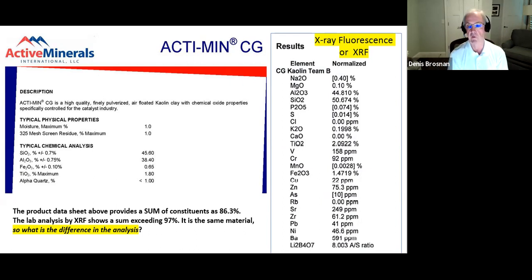Well, this full analysis was not really necessary for a product data sheet, which is showing you typical values. The chemical analysis gives you minor constituents as well. But if you add all those up, we're going to be pretty close to 100%. Now, I'll be frank with you, I didn't add them all up. Some of the numbers in brackets there are below the detection limit of the device. And typically you'll see that when they're below about 1% or so.